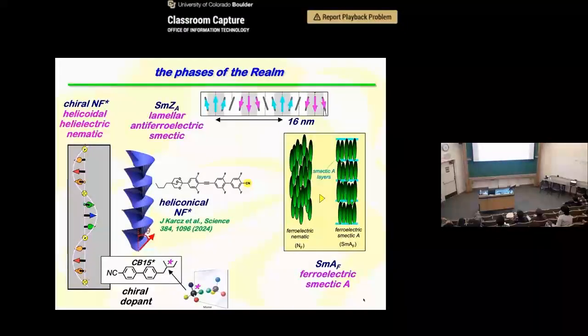There's a ferroelectric smectic A phase. So you have ferroelectric nematic, you cool the phase, you cool this, and the molecules sort of shift up and down and sort of get next to each other and form layers, okay? So here the molecules are normal to the layers, so that's a smectic A. Here the molecules are laying down parallel to the layers, so that's a smectic Z. So this is a ferroelectric smectic A.